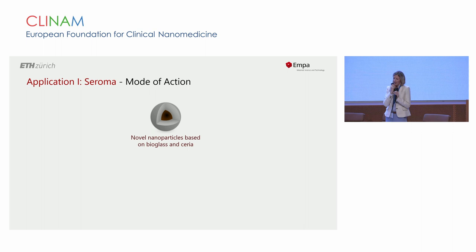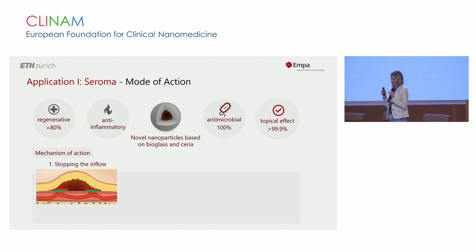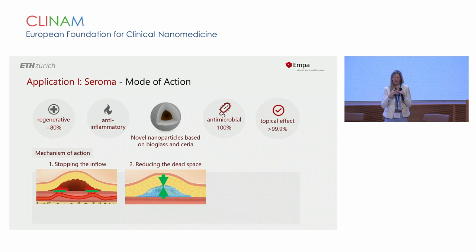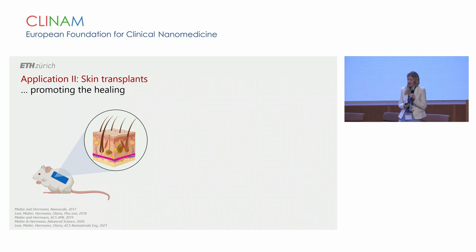For the seroma case, we see the following mechanism of action of this nanoparticle-based glue. It has all kinds of different properties and unifies them nicely. On one hand, it stops the inflow of serous fluids into the cavity. It reduces the dead space by creating adhesions between the two sides of the seroma cavity. And it prevents infections by the mechanism I just showed, which is based on reactive oxygen species.